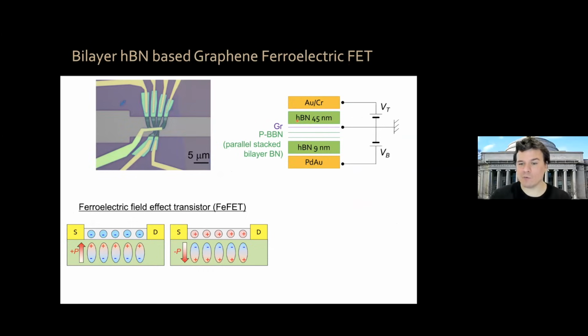We encapsulate, we place on top graphene. Graphene is now just a sensor to sense the ferroelectric state of this parallel stack boron nitride bilayer. We have thicker hexagonal boron nitride just as a dielectric, and we have gates, bottom and top gates, to be able to apply an electric field in the perpendicular direction, so that we can now make a ferroelectric field effect transistor, okay? Where the state of conduction of the graphene, the resistance of the graphene, is going to depend on the polarization of this ferroelectric material, okay?